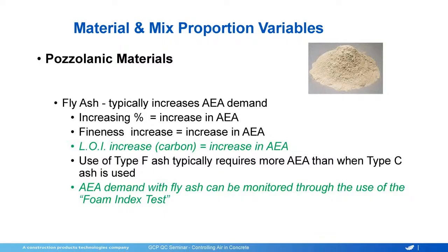Okay, fly ash, and I know that in architectural plants, it's not always used. There are some that do that, but fly ash typically causes the air entrainment dosage to be increased. That can be because of the fineness. It can be because of the LOI. So if you have a higher LOI, or if you have a fluctuating LOI, it can be a real challenge to get consistent air. So the LOI, the carbon in the fly ash, will act as a sponge and absorb that air entraining agent. And so it's not available to help stabilize those bubbles. So the higher that number is, the more difficult it is to get consistent air.